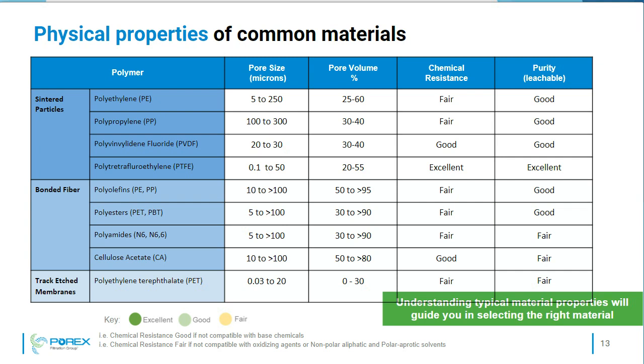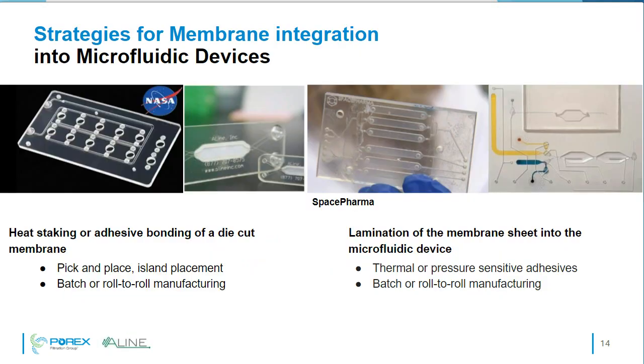So we now want to look at strategies for membrane integration. There are typically two ways we can integrate a membrane into a microfluidic cartridge. You can either go the route of using die-cut or laser-cut membranes that are heat-staked or adhesive bonded as an island placement, so a small surface area of the device is actually covered with the membrane. Examples are shown here on the left with some of the cell culture and organ-on-chip devices. Or, in the alternative, you can use lamination of the membrane sheet as a full surface area of the membrane. This is typically achieved with thermal or pressure-sensitive adhesives.